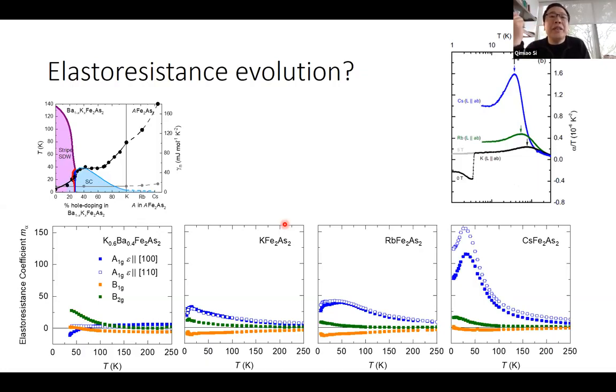is not signifying any nematic tendency towards nematic order. Correct. Because the overall state, for instance, if you look at the resistivity, there's a crossover happening around 50 Kelvin, and if you look at anything else, specific heat, it's developing. Is that a fair understanding? Yes. So this temperature dependence in the cesium, with this peak or this large enhancement, we see in basically everything. It's related to this coherence-incoherence crossover behavior. Yeah, it's something that I would see in heavy fermions, for instance. Exactly, but it's a symmetric effect. It has nothing to do with distortions. It has nothing to do with nematicity.